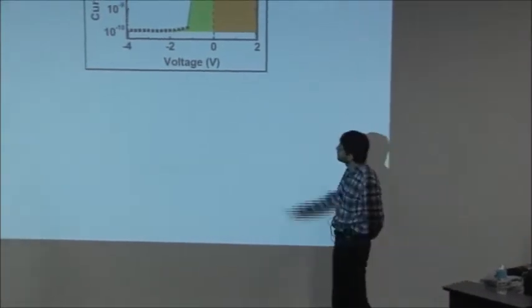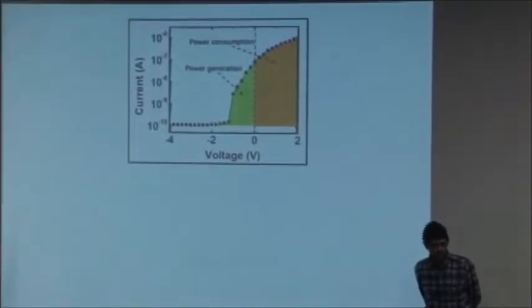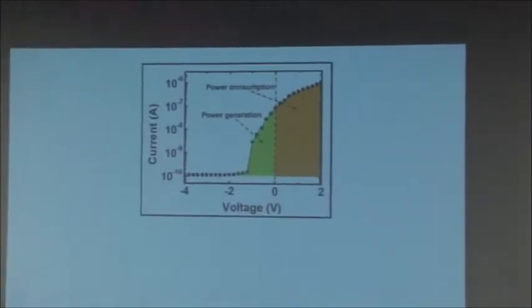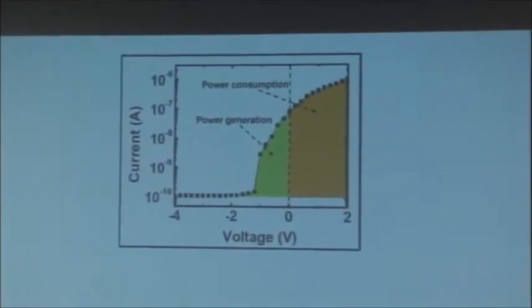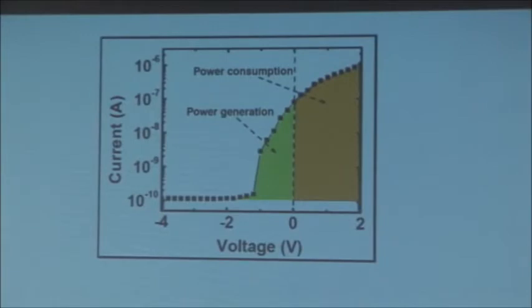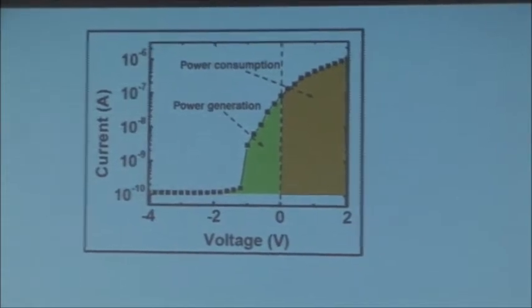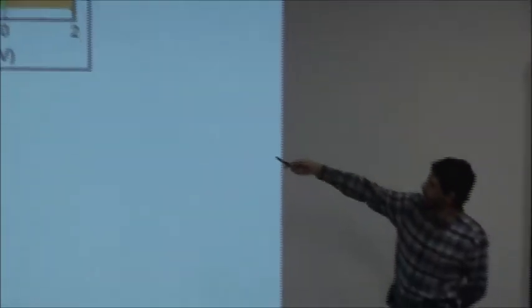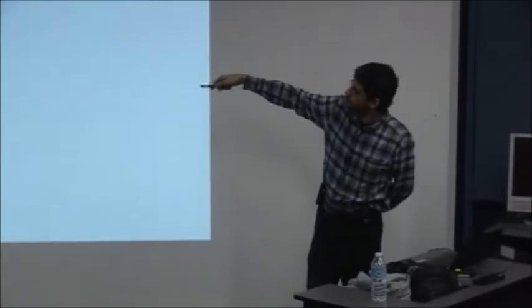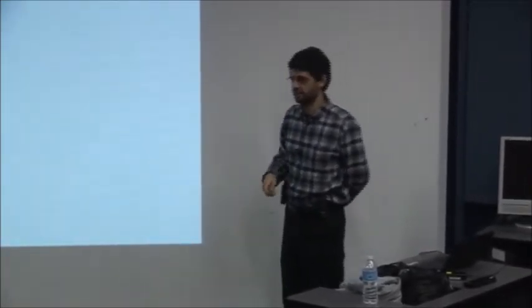Now, if you look at the scale here and do the math and calculate the efficiency, you might attack me right away and say this is completely useless, because efficiency is very poor. You know, remember, this is the first prototype without any engineering and so on. The efficiency of this very first prototype, at the best point you calculate, is about 10 to minus 6%. Okay. So the reviewers, of course, were saying this is noise, this is useless, it's not practical.